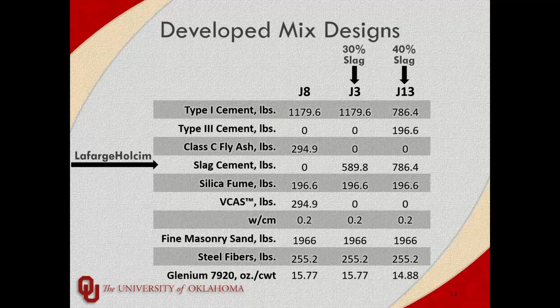And we went through a bunch of series. We labeled them by letters, series A all the way up to J. Series A started out with the mixes from FHWA, and then through all of our reactivity studies and our particle packing and looking at all of our different SCMs, we got to series J, where we combined all the promising things that we saw into a bunch of mixes, and then we narrowed it down to these three to characterize. So J8 is the only one that uses the VCAS.